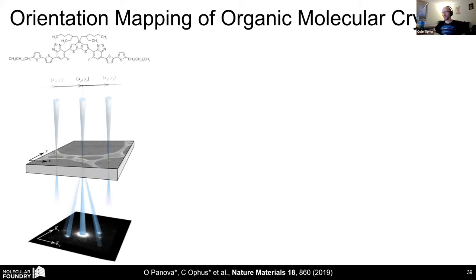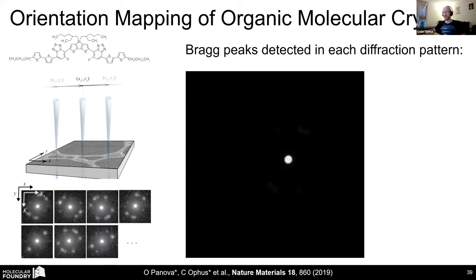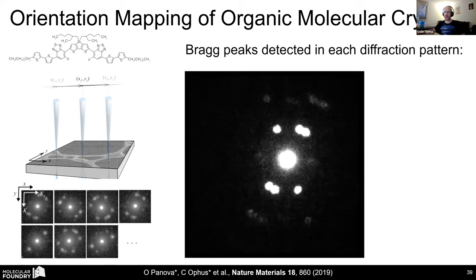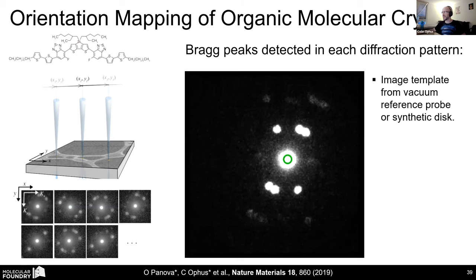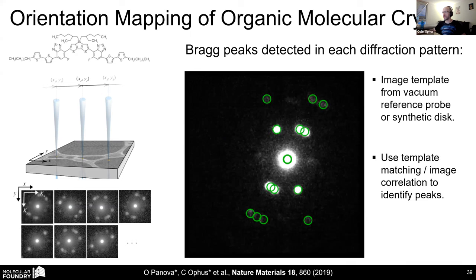I mentioned our interest in soft materials. So this is a small molecule, polymer-like structure. If you look at the diffraction patterns of these materials, you see almost nothing. You really have to enhance the contrast to be able to see the diffracted bright spots. And the beam very much destroys this material, so we have to take about a 10 nanometer step between adjacent probes into undamaged material to be able to characterize them. But we are able to see the primary diffraction spot here. This is the pi-pi stacking of this material. And then we use data analysis methods to reconstruct the macrostructure of these samples.